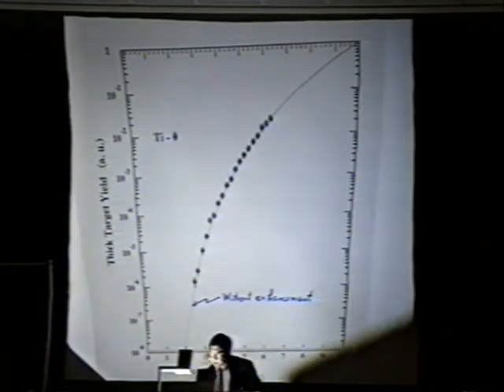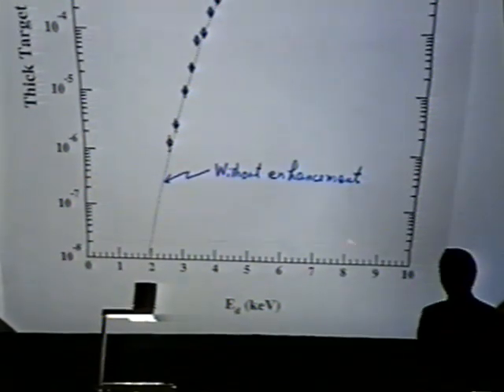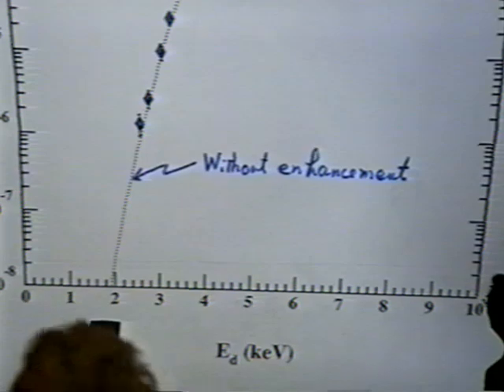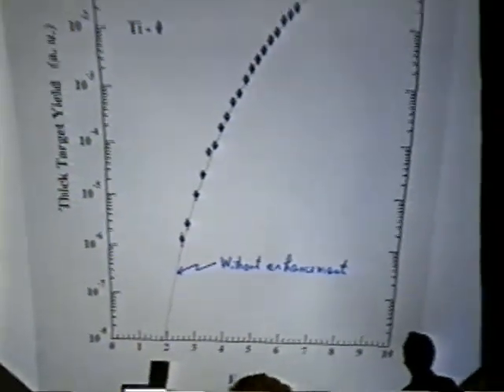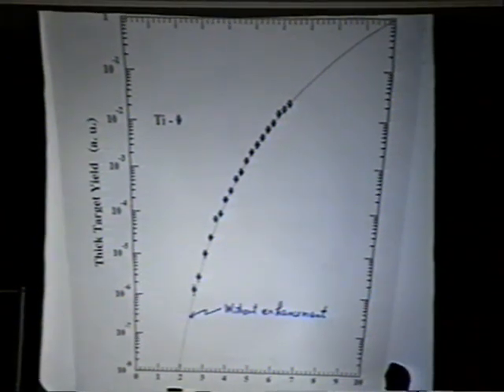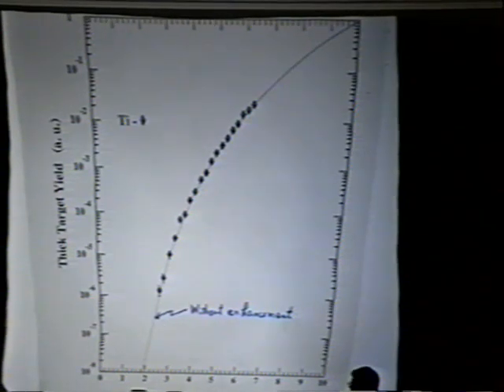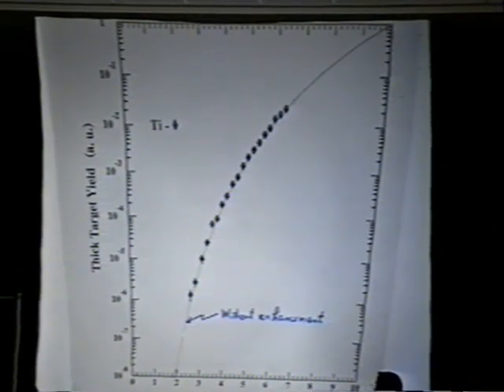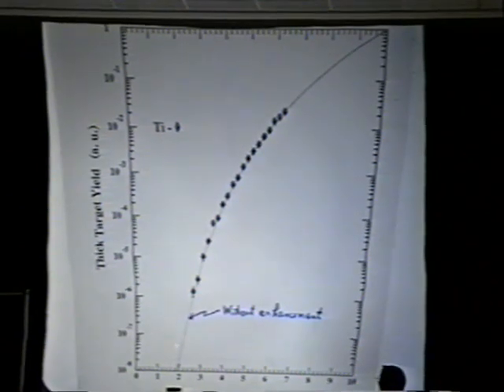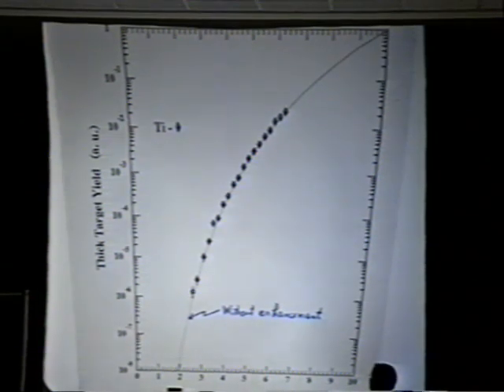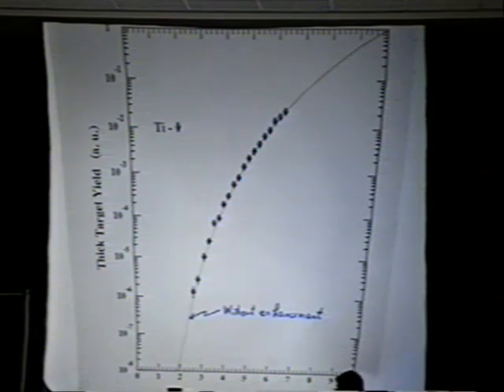What I showed you here is the previous result. For example, this is for titanium. And you see the energy scale is from 2 keV to something around several keV. And this is the so-called thick target yield, which is normalized at 10 keV. And this dotted line is the prediction from the ordinary cross sections. In this case, there is almost no enhancement. So this is the standard. We can say, actually, there is a little bit of enhancement around here, but let's say only a 10 or 20% enhancement. Now, I'll show you the very recent result.